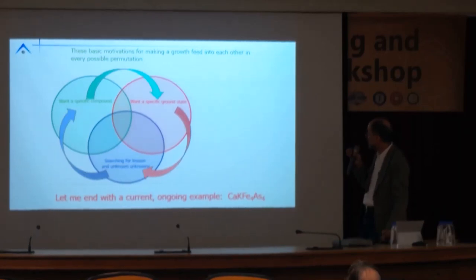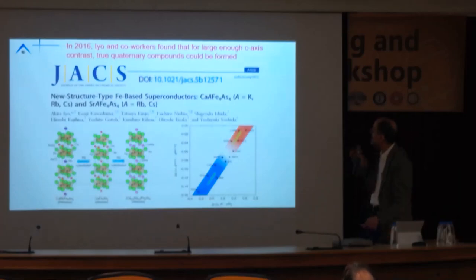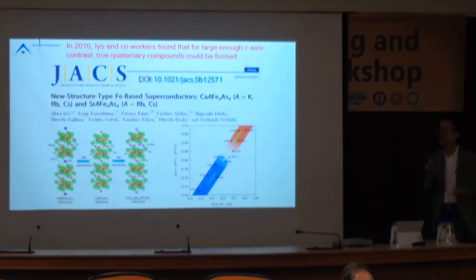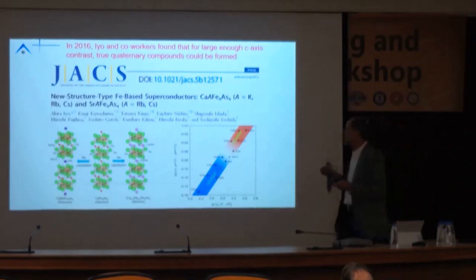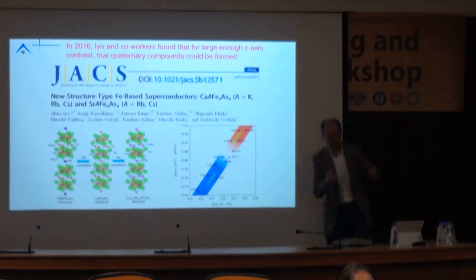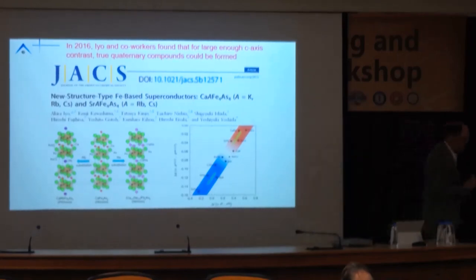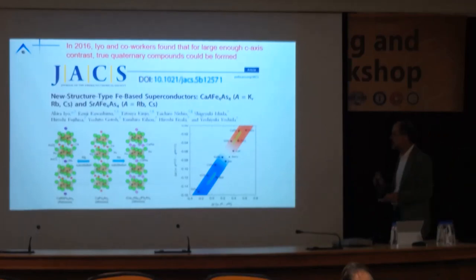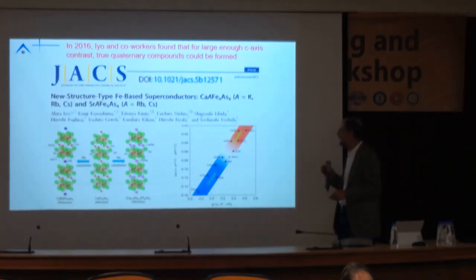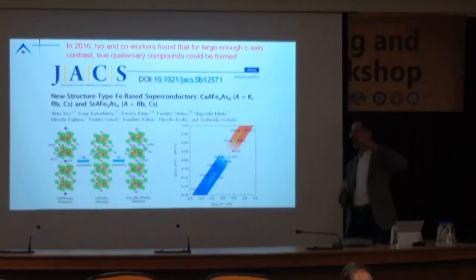This is calcium, potassium, iron, arsenic. This is a material that in 2016, Iyo and co-workers discovered as a quaternary compound associated with the alkali and alkali earth iron arsenic 2 materials. These are materials that you can grow: barium iron arsenic 2, potassium iron arsenic 2, calcium iron arsenic 2. They have different c lattice parameters, and what Iyo and co-workers found is if you maximize the contrast